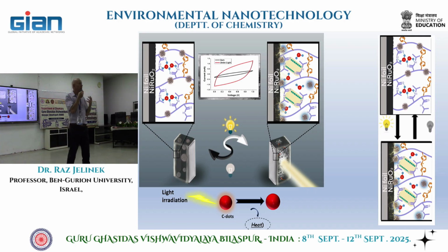Now, if the polymer becomes hydrophobic, what will happen to the carbon dots? The carbon dots, initially, they sit on the polymer. But at higher temperature, we have a hydrophobic polymer. The carbon dots don't feel good anymore. They cannot attach to the polymer. The polymer is hydrophobic. The carbon dots are hydrophilic. They are charged. So they will need to go to the solution. They will have to leave the comfortable home of the polymer. If the carbon dots are in the solution, they will be an excellent electrolyte for the supercapacitor.